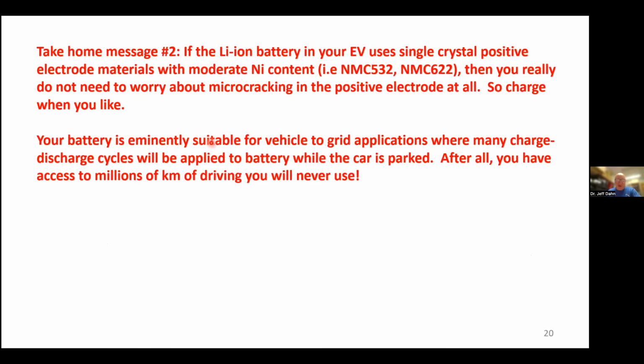So the take-home message here, number 2, is if the lithium-ion battery in your EV uses single crystal positive electrode materials with a moderate nickel content, like NMC 532 or 622, then you really don't need to worry about microcracking the positive electrode at all. So in this case, you can charge when you like. And your battery is eminently suitable for vehicle-to-grid applications where many charge-discharge cycles will be applied to the battery while the car is parked. After all, you've got access to millions of kilometers of driving you'll never use.